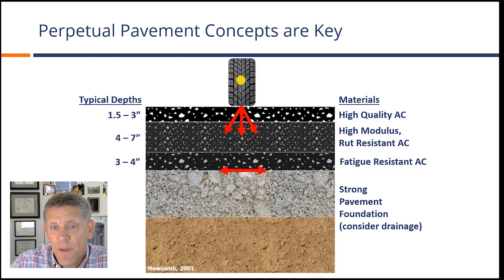Remember that a perpetual pavement is one that does not have deep structural distresses, meaning bottom-up cracking, cracks that initiate and propagate to the surface of the asphalt, and we don't have deep structural rutting. So it all begins by focusing our attention on a strong pavement foundation that considers drainage. On top of that, we have these various materials, and we're selecting high-quality rut-resistant materials in the middle and upper layers to combat rutting of the AC mixture.